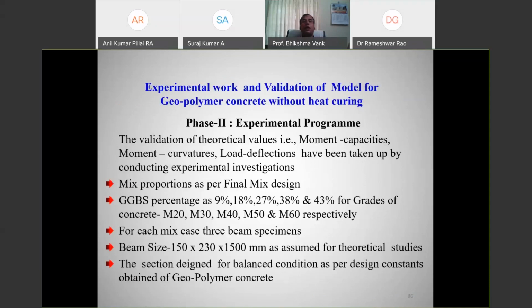Similarly, experimental work and validation of the model for geopolymer concrete without heat curing has been done. Mix proportions as per the final mix design have also been arrived at, M20 to M60. For each mix case, 3 beam specimens have been cast, that is 150 by 230 by 1500 mm. Please understand, whatever theoretical moments we got is for the 150 by 230 mm cross section with 1500 mm length. Similarly, the same cross section and the same area of steel have been taken for experimentation, cast with the same grades of concrete, and then the experimental moments were arrived at.